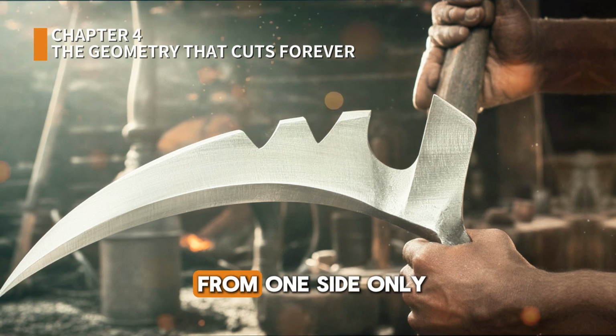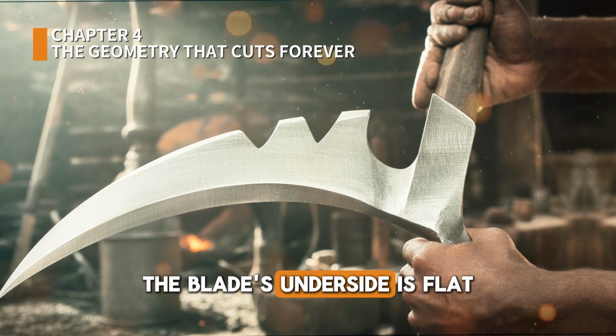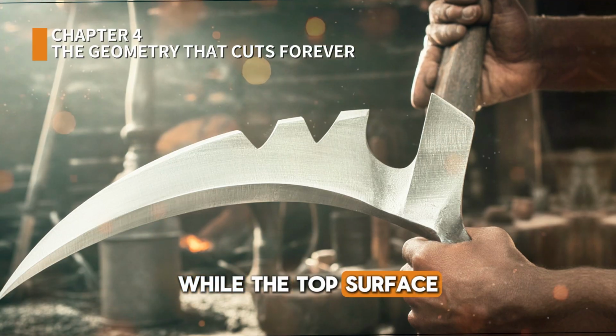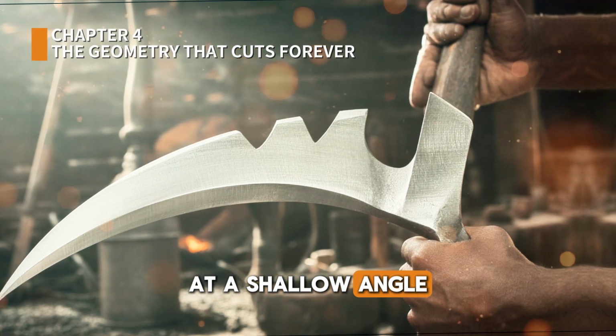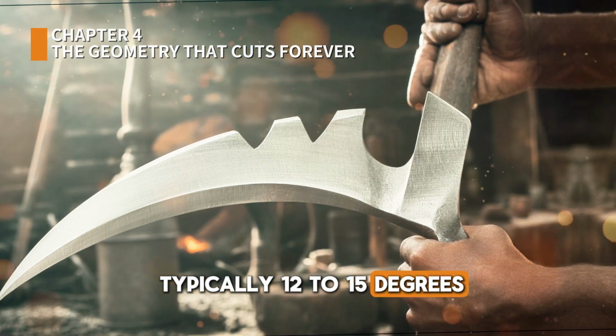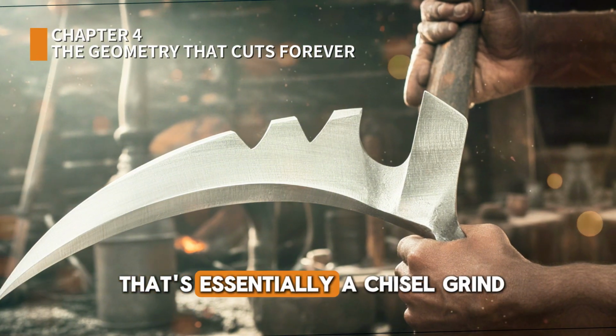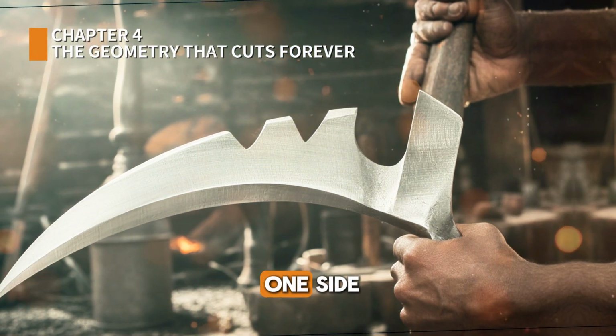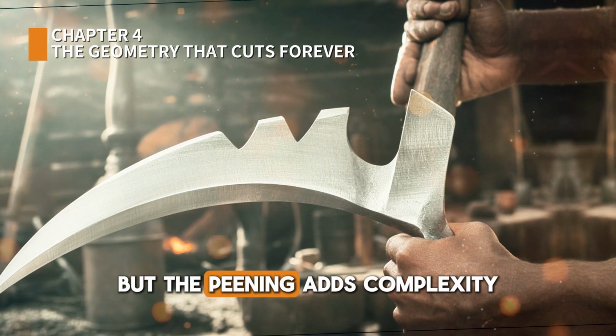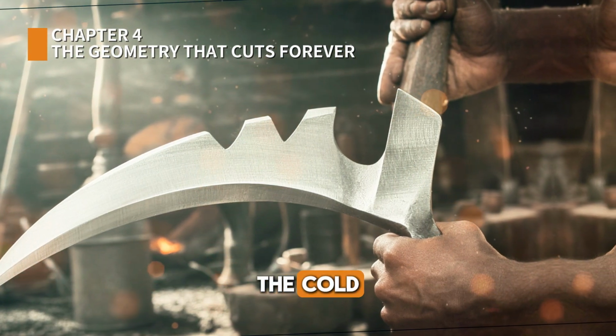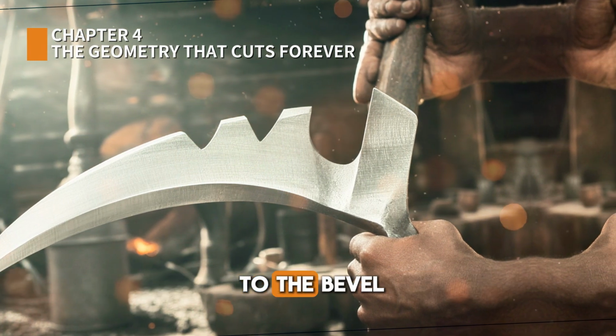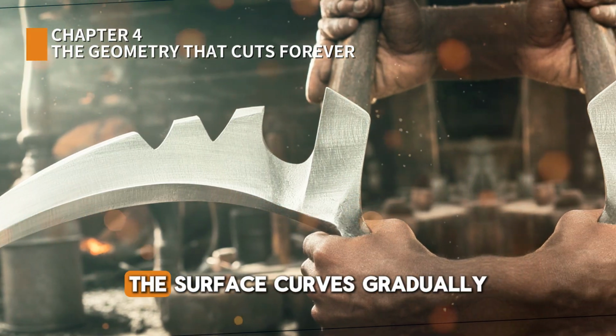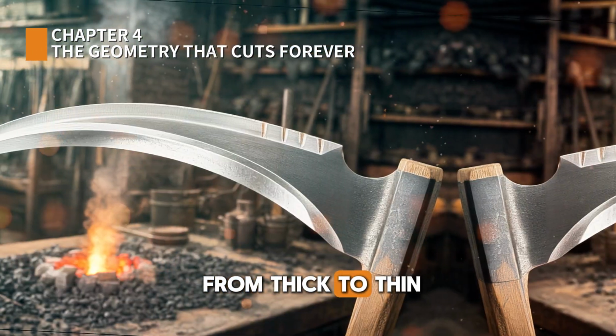The edge is ground from one side only. The blade's underside is flat, while the top surface curves down to the edge at a shallow angle, typically 12 to 15 degrees. This creates an edge that's essentially a chisel grind, all the bevel on one side. But the peening adds complexity. The cold hammering creates slight convexity to the bevel instead of a flat plane. The surface curves gradually from thick to thin.